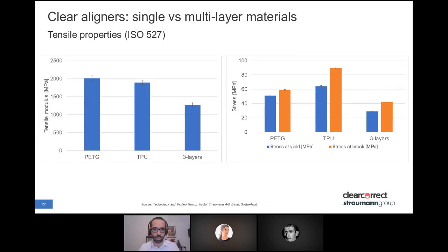And as you can see, in terms of tensile properties, for example, the 3-layer material is a bit softer and also a bit less strong, which means indeed we are not using this for longer than a few weeks or a couple of months, compared to the other two that can also be used as final retainers, meaning that they can be in the mouth for 6 months or more.